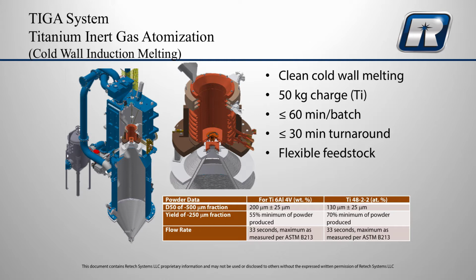It's a cold wall induction melt bottom pour gas atomization process. It's a clean melting, if you will, in a cold wall induction crucible. As many of you may be familiar with that, typical charge sizes range anywhere from 40 to 50 kilograms for titanium. We can melt and atomize in less than 60 minutes.